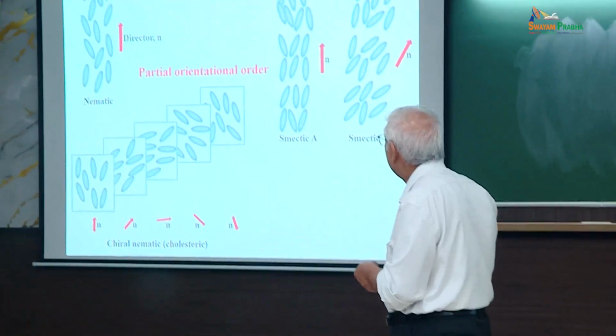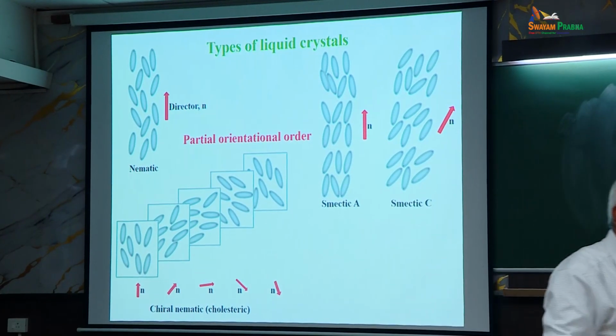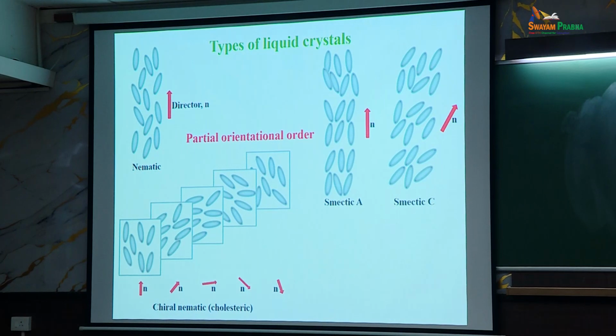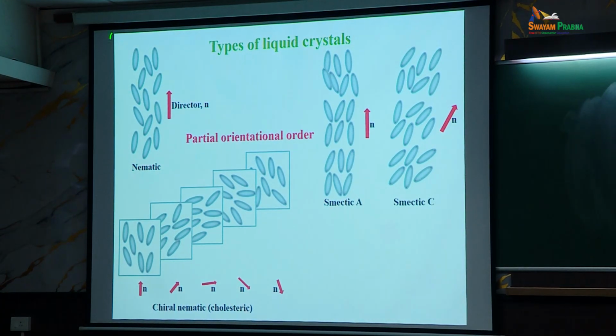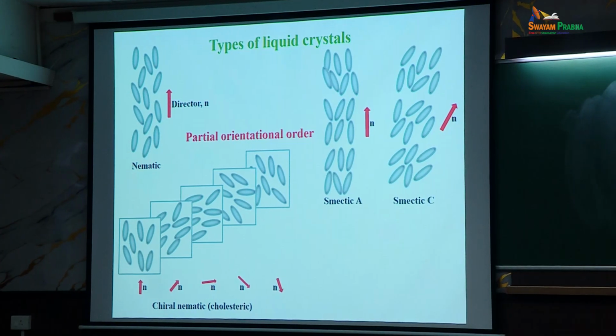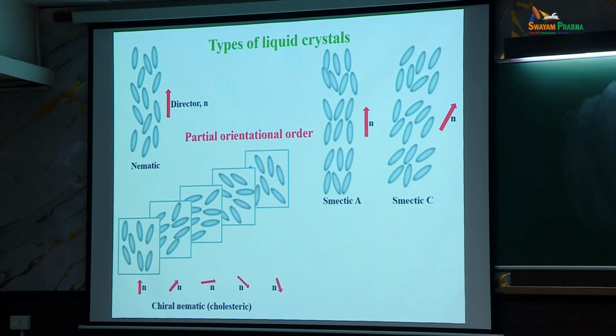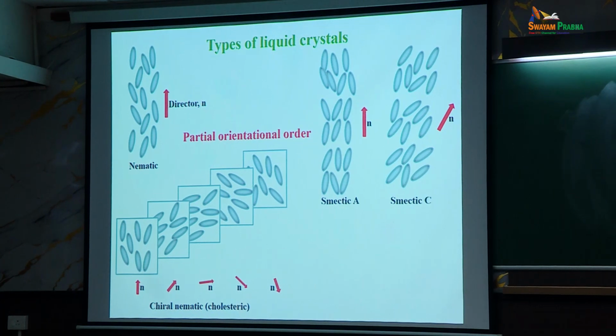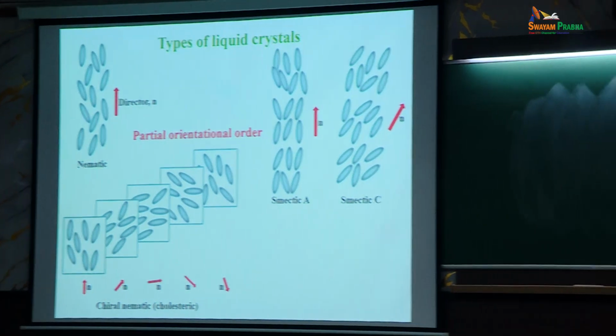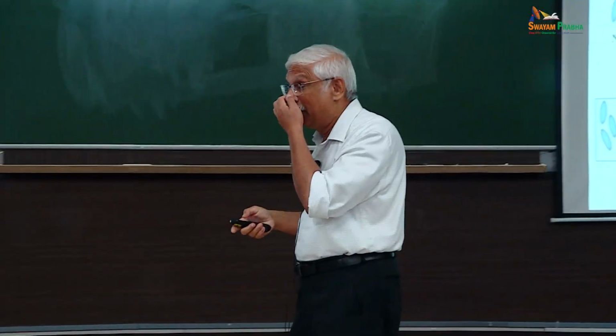But then the term liquid crystal itself is very evocative. It tells you there is some liquid property and some crystal property. These are called partially ordered. Look at this picture. If I ask you, are they ordered? It's a tricky question. They are not ordered like a crystal, but you can see they are all elongated ellipsoidal molecules, and they are all oriented roughly in that direction. There is something usually called a director axis. Along that axis, there is a small distribution of angles. Some theta angle, if you take, will have a distribution in the range of some 5 to 10 or 15 degrees. But all of these are ordered roughly. So that is a partial ordering. Now this is very important.